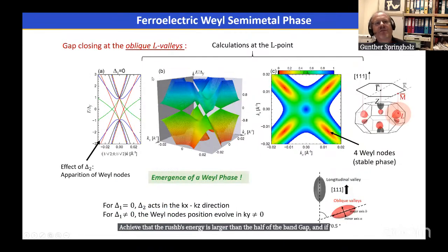And the interesting physics occurs here at the oblique valleys of the system, shown here in the calculations, where one finds that instead of this ring, we have 4 band crossings, band minima at these points that are split in momentum. And this indicates the emergence of a Weyl phase of the system, a new Weyl phase with 4 Weyl nodes appearing at each of the band extrema at the L points of the system.